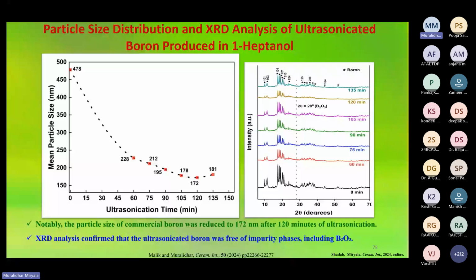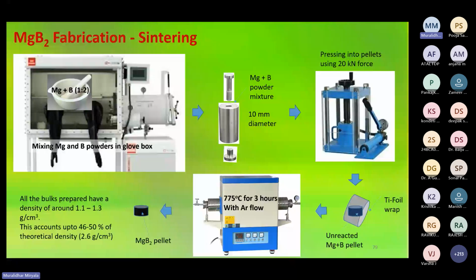Then the XRD results, you can see in the right-hand figure: XRD after several hours of ultrasonication in heptanol, from 0 minutes to 135 minutes, still shows no contamination. Normally B2O3 peaks are one of the major issues here, but we are not seeing anything. It was free of impurity phases. Such boron powders can be utilized in the MgB2 fabrication.